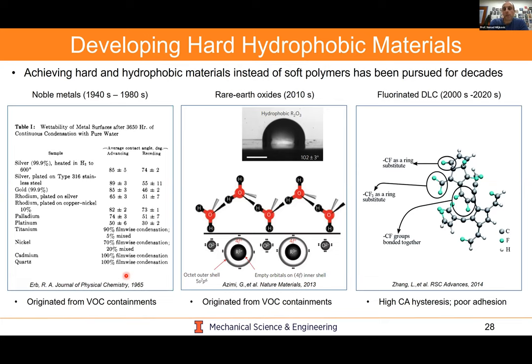And so here we were inspired by previous work looking at noble metals and rare earth oxides, which are basically non-organic compounds, which were claimed to be hydrophobic, but it turns out they were not hydrophobic at all. They were just being adsorbed with volatile organic compounds and becoming hydrophobic over time. Another class of materials, which have carbon, so you could call them organic, but they're not quite organic because they don't form typical hydrogen and carbon bonds that you would see in these thin polymer films,